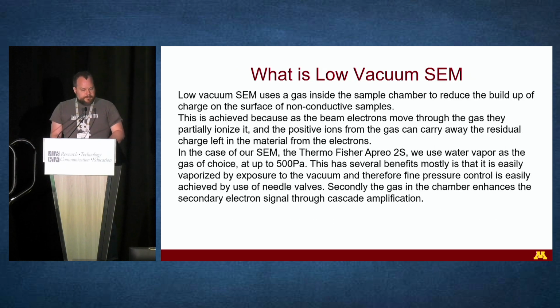So the low vacuum SEM works by essentially bleeding a gas into the chamber. In the case of our SEM, we actually use water vapor. It's very easy. You just have a little Erlenmeyer flask of water connected by a needle valve to the chamber. The computer controls the needle valve, opens and closes it to let the water evaporate into the chamber.